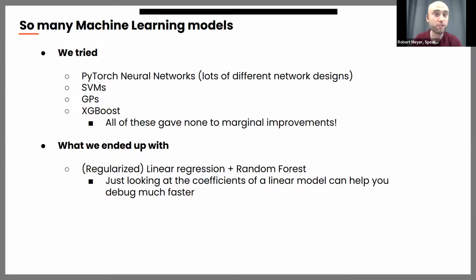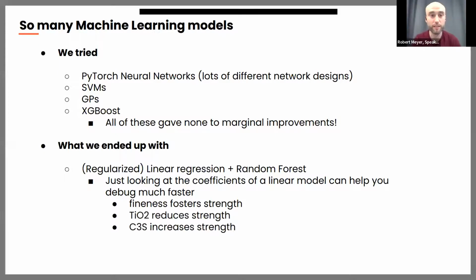Because if the coefficients show things that are known to cement process engineers, then it's great, because then we can use that in steering. For example, we steer the cement by modifying the fineness, so the coefficients should pop that out too. There should be a strong relationship between the fineness of the material and the final resulting strength in how the model makes the prediction. Or things like titanium dioxide reduces strength, or C3S fosters strength. If that pops out in the linear coefficients, we're happy, because that tells us the model picked up something meaningful. So, real machine learning in production: simple models are your friend.